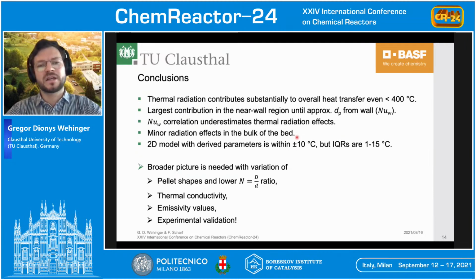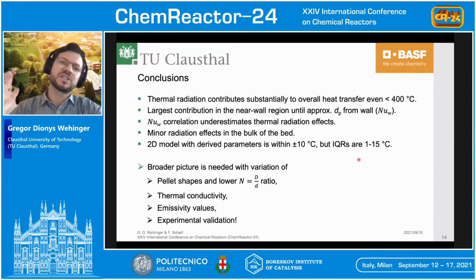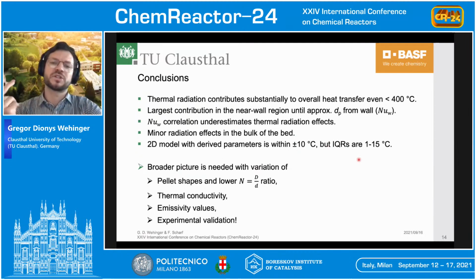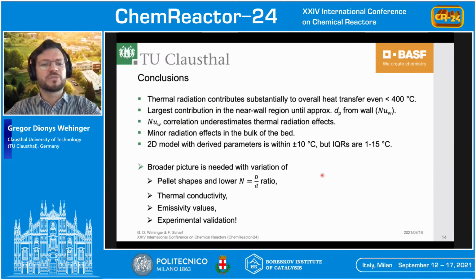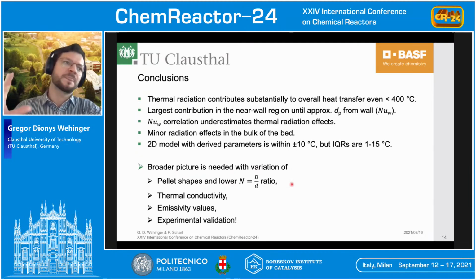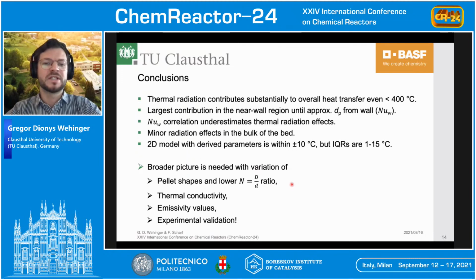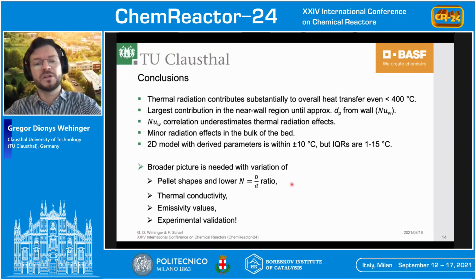Minor effects can be seen in the bulk. But we also have to keep in mind that in a CFD simulation, we still see some huge temperature differences, depending on where you are on your cross-section. But definitely we need a broader picture, especially for even lower D by D ratios and different particle shapes, because then obviously thermal radiation might play a more severe role.